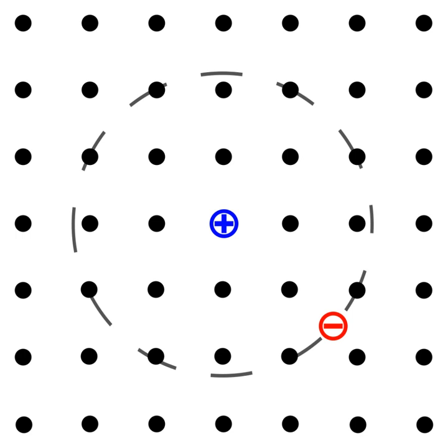The hallmark of molecular excitons in organic molecular crystals are doublets and/or triplets of exciton absorption bands strongly polarized along crystallographic axes. In these crystals, an elementary cell includes several molecules sitting in symmetrically identical positions, which results in the level degeneracy that is lifted by intermolecular interaction. As a result, absorption bands are polarized along the symmetry axes of the crystal. Such multiplets were discovered by Antonina Prikhotko and their genesis was proposed by Alexander Davydov. It is known as Davydov splitting.